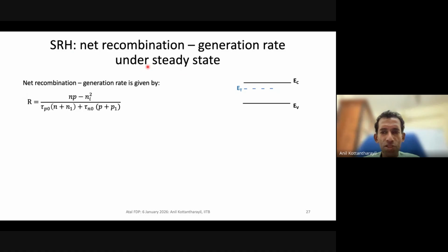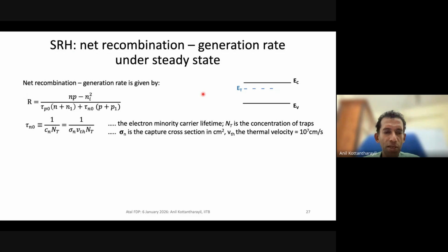Now, for the SRH recombination, you can see there are a lot of equations here. But one thing I would really highlight is that the recombination rate, of course, depends on the electron and hole concentration, but also on the properties of the defect level that we have seen in the forbidden gap. There is something called the capture cross section, and I'll not go into the details, but this is very important. This talks about the density of the impurities. So the higher the density of impurities, the lower is your lifetime. Very important consideration. Lower lifetime means what? You have a higher recombination rate, right? Recombination rate is delta n divided by tau. So the smaller the tau, the higher the rate.